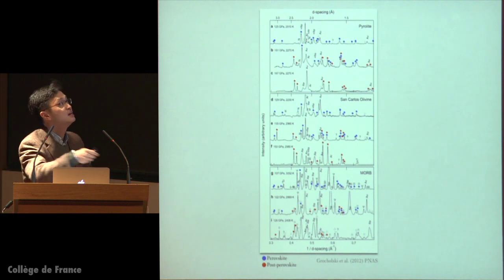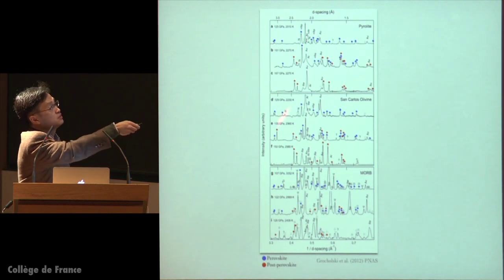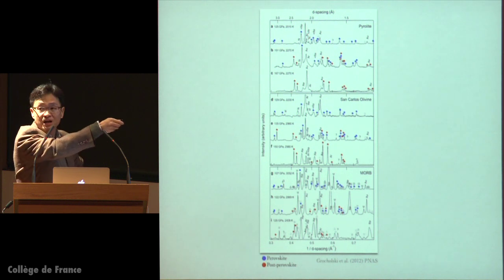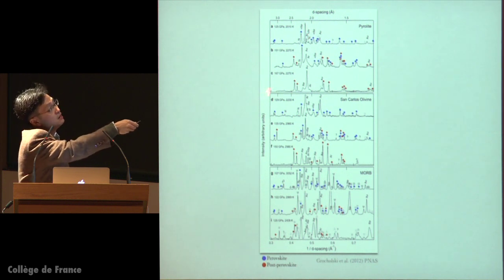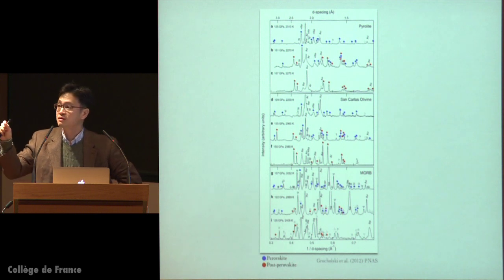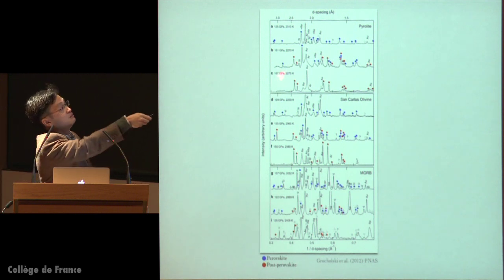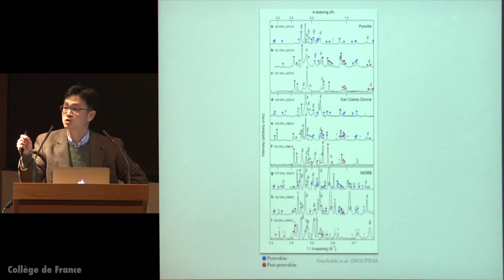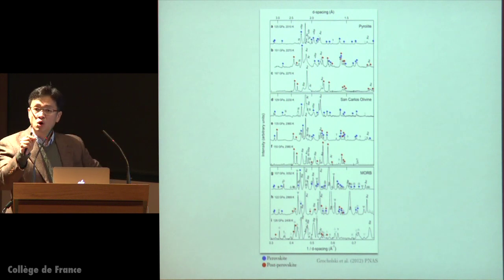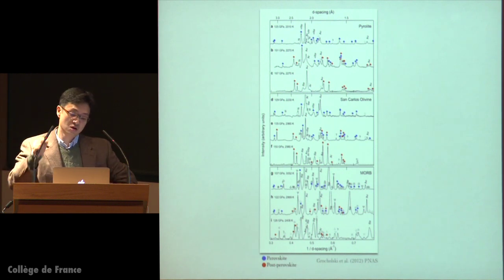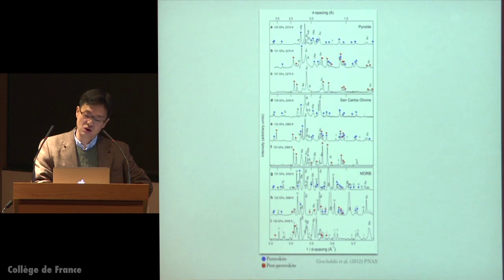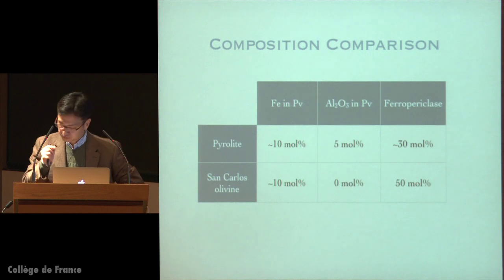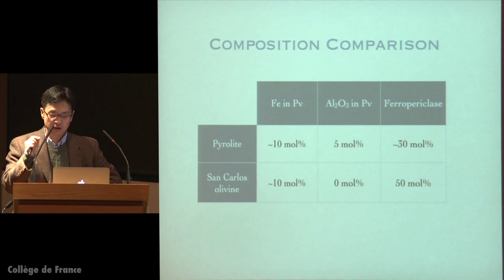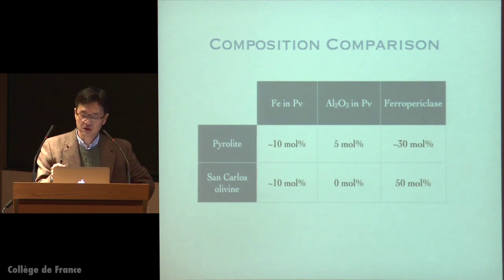So basically, we see a bunch of diffraction lines from the crystal structure that we can use as a fingerprint of different phases. And you can see that the top portion of each diagram shows the perovskite pure stability field, and the red shows the stability of pure post-perovskite. And the existence of both red and blue obviously means the mixed phase region. And all these X-ray diffraction patterns were measured in situ at high pressure and high temperature during the laser heating experiment at a synchrotron.